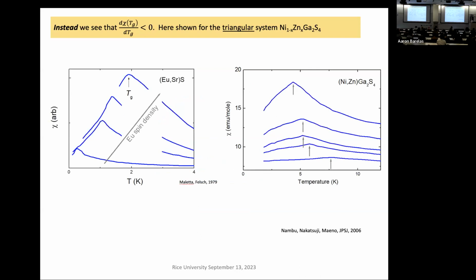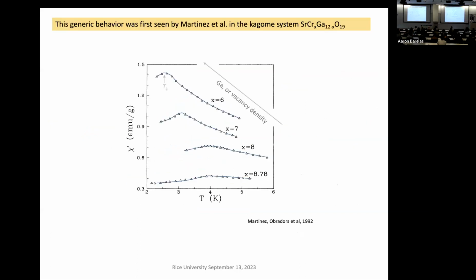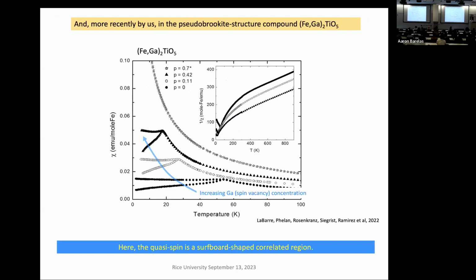So this is the two. This is a difference where you don't have to know anything about the physics or the materials, but you can tell that these are two qualitatively different behaviors. This has been bothering me for almost 30 years. Actually, since this paper appeared. So this is the first demonstration of this by Obradors's group, showing in this chromium system that as you put in vacancies, the signal goes up. Right? So that confirms the quasi-spin idea, but the collective temperature goes down.